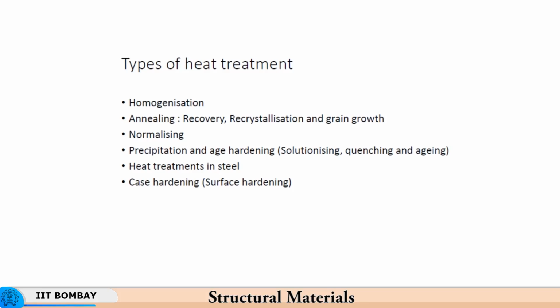Same is the case with many applications where you do not want the crack to originate at the surface, like in a rotating bending type of fatigue. For example, railway axles undergo rotating bending type of fatigue damage. So, if the surface of the axle is hard enough, then to start with, the originating of the crack itself will be a little difficult. And so, during the process of heat treatment, what you will do is you will harden the surface selectively.